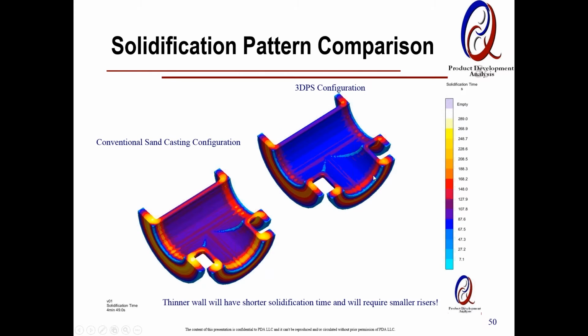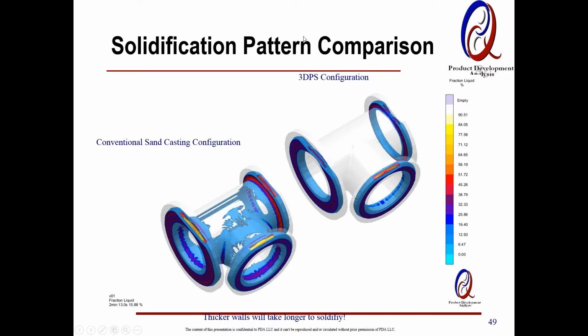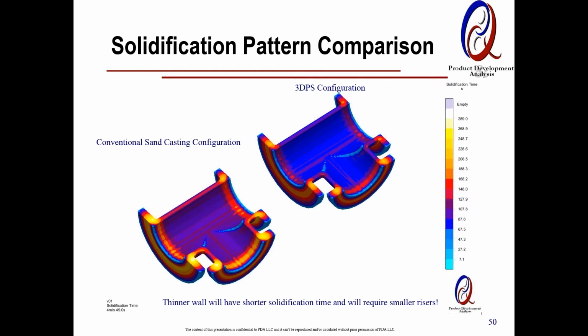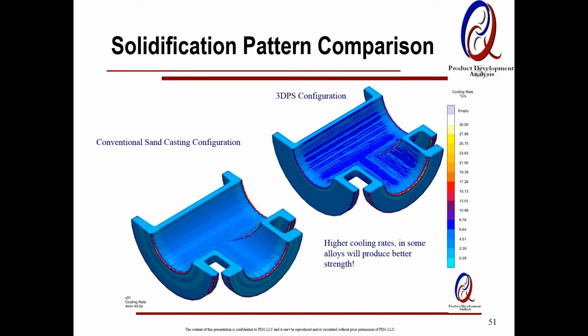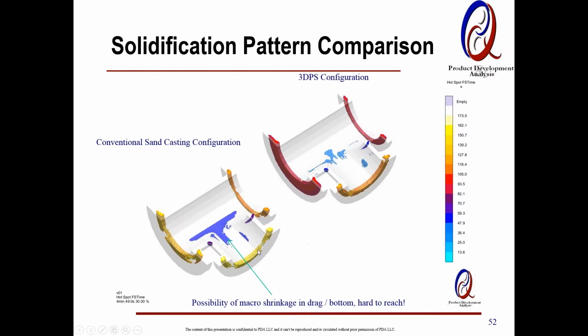And another thing we saw happening is it improved the quality with shrinkage predictions, and because of the cooling rates, this is with the conventional design. This is in the drag, which is very difficult to reach. You almost have to use a cast chill. Here, you have the shrinkage within the acceptable level, much reduced, and overall it's a win-win situation.